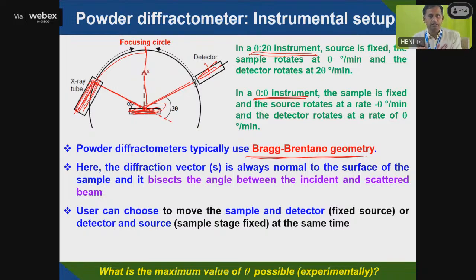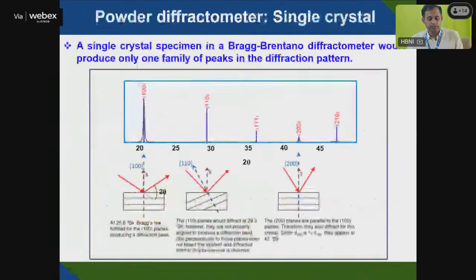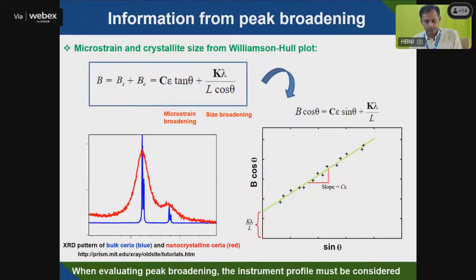So in the case of 2theta, mostly you can get 2theta values of 140 to 160, where theta can be changed up to 70 to 80 degrees. That is the maximum. Otherwise, the detector and source will collide with each other. You can't go beyond that.